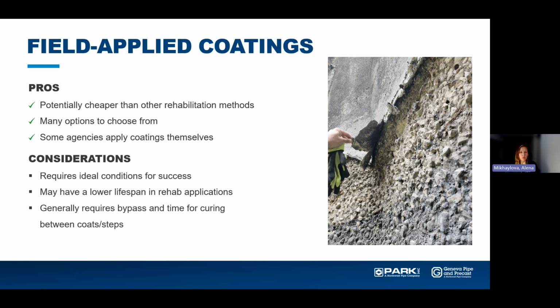And for these to work, they definitely work. They create a protective barrier between the corrosive environment and the concrete wall. But with time, they can physically degrade, chip and crack, and you may still have corrosion behind the liner. In fact, one of the main failure modes is the pressure that you get behind the epoxy liner. If you have infiltration behind the wall, it will get in between the epoxy liner and the concrete wall, and it starts cracking under the pressure and chipping away gradually. Once you have a crack, you're going to have continuous corrosion of your structure. So this is an example of a failing field-applied coating.